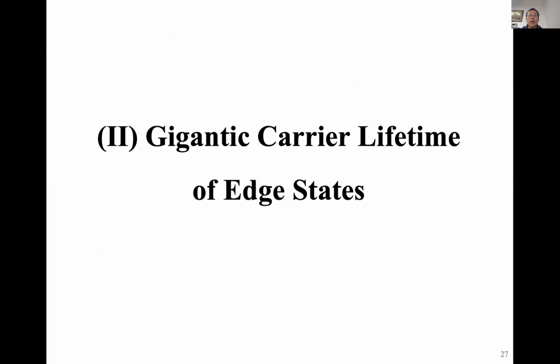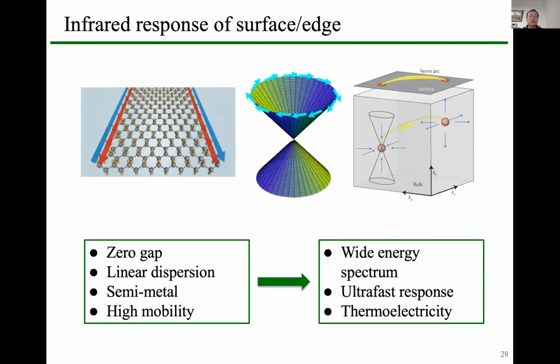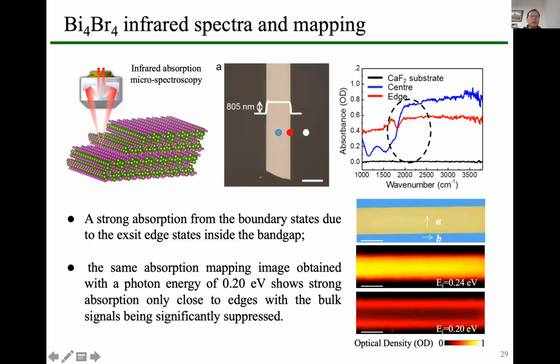So we have edge states, and then the lifetime would be an interesting problem. The reason we do this work is because we are interested in infrared absorption for infrared detector applications. I'm not going to say too much about this. The material is still these exfoliated nanowires, one-dimensional wires, and we use infrared absorption spectroscopy to demonstrate the existence of robust topological edge states. This experiment was actually done very early, maybe 3 or 4 years ago, but to publish this paper we spent a lot of time on further experiments.